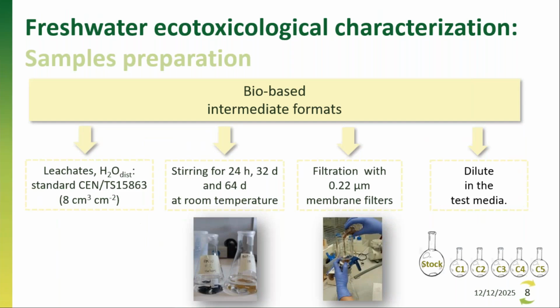With regard to the bio-based intermediate format, we have followed also a standard that is already available, which is the technical specification published by CEN, which describes the procedure for preparing liquids. In this case, small squares, 1 centimeter squares of each of these intermediate format materials are deployed in 8 milliliters of distilled water, and are also left to stir for 24 hours, after which they are filtered, and then the dilutions are prepared according to what we need. In this case of the bio-based intermediate formats, as they were the closest to the end product, we found out that the 24-hour leaching period was not very relevant in terms of environmental realism.